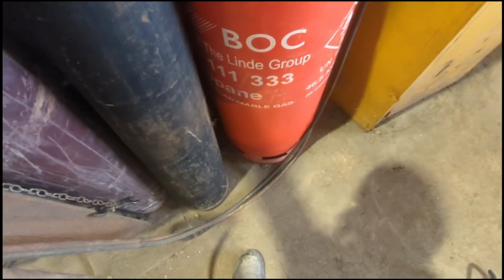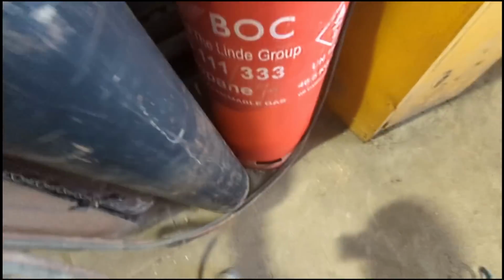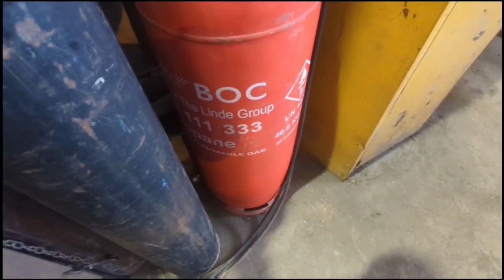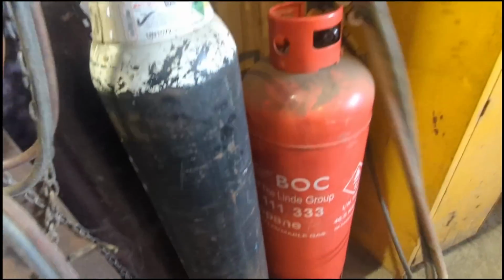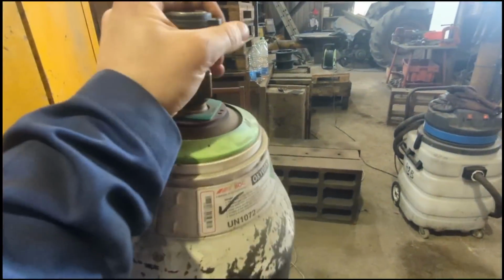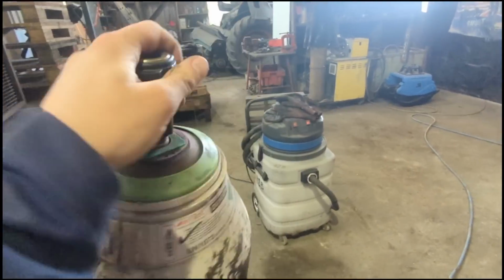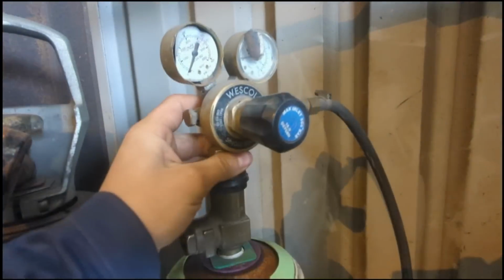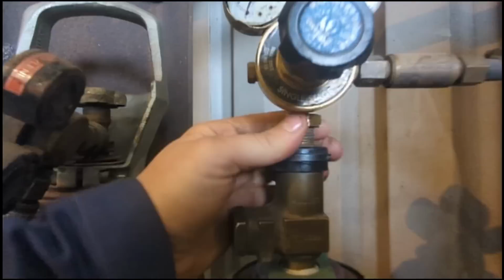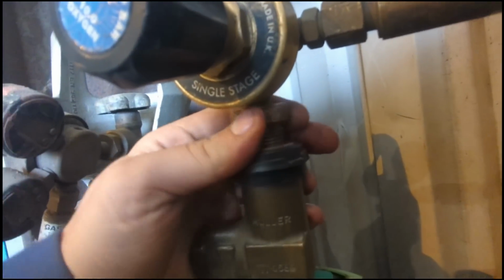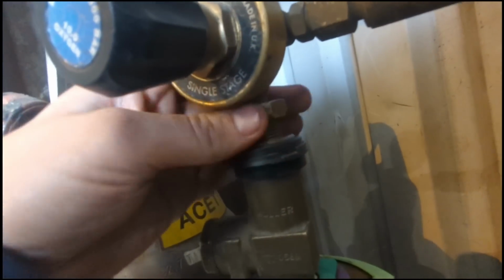I fired an absolute stack of oxygen and some propane for preheating, as the preheat was such an important part. The reason for preheating is to negate unwanted stresses during the welding and to keep the hydrogen low in the actual weld itself. This is important even though we're performing normalization after the welding.